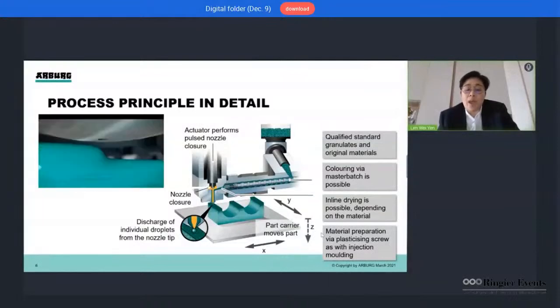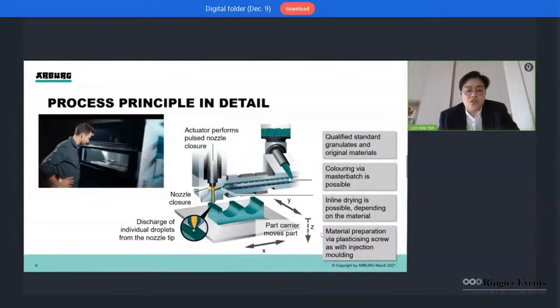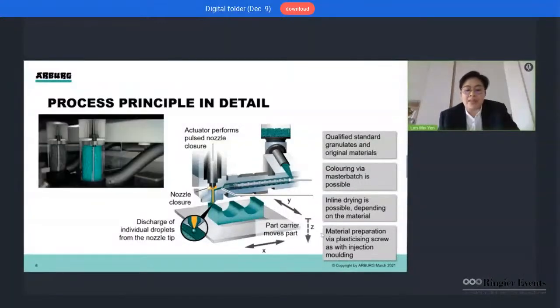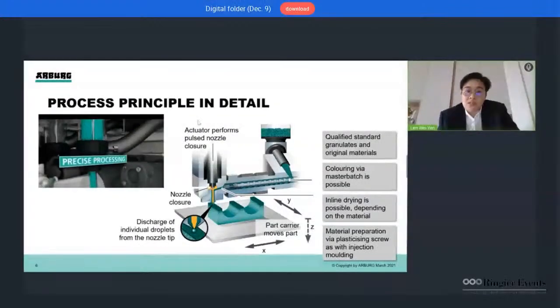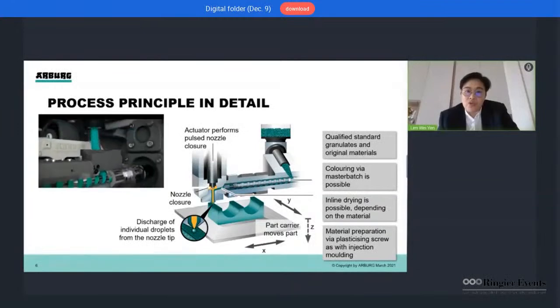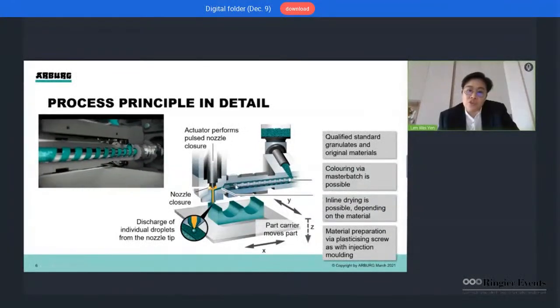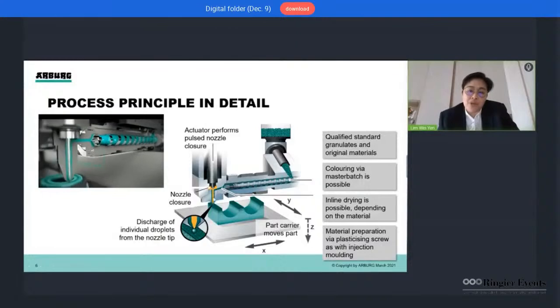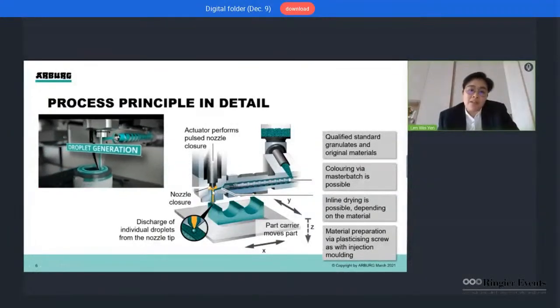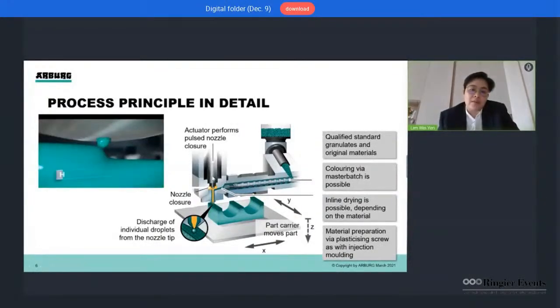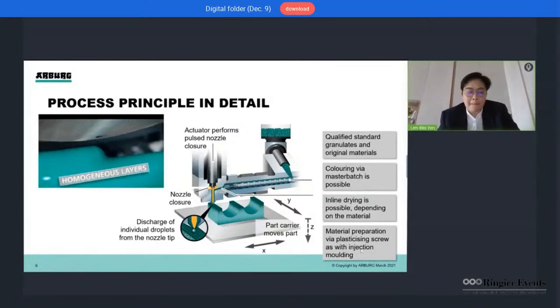The nozzle is closed by an expansion of the piezo actuator located in the top area of the discharge unit, and when the nozzle is opened by the mass pressure, the material flows through a 10 micron gate at the tip of the nozzle. This is the piezo actuator here. When the melt material pushes forward, the mass pressure pushes the needle up, touches the piezo actuator, and the material comes out from there.